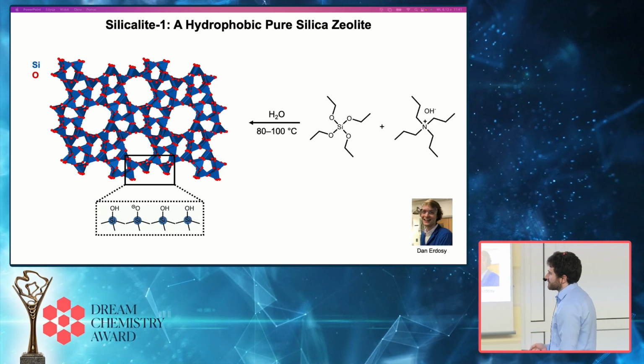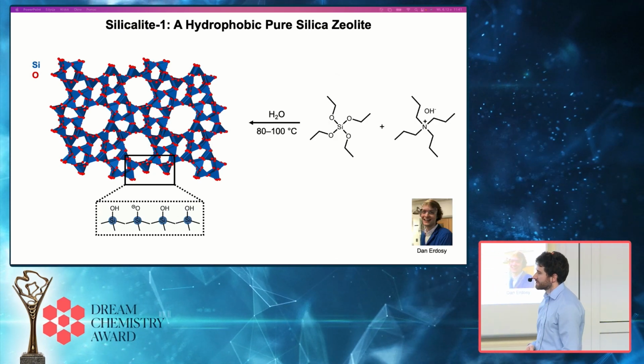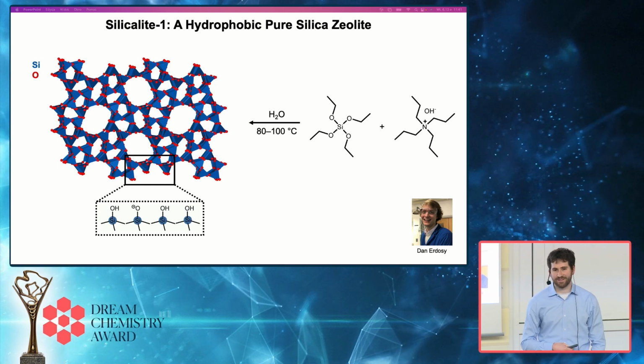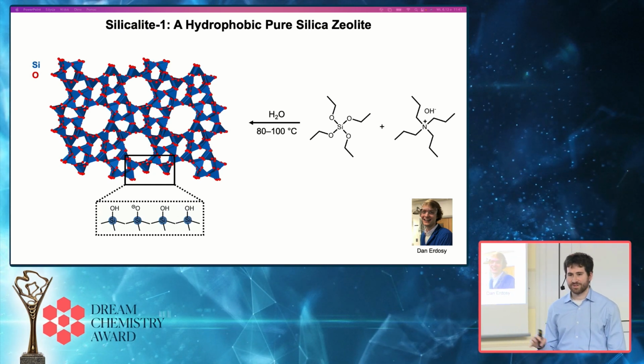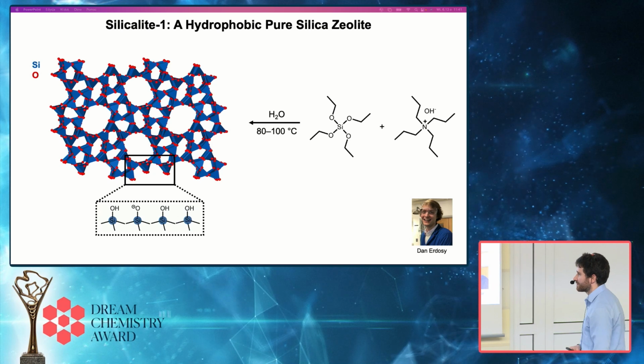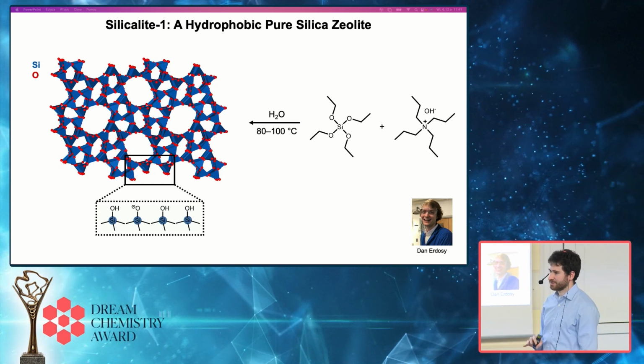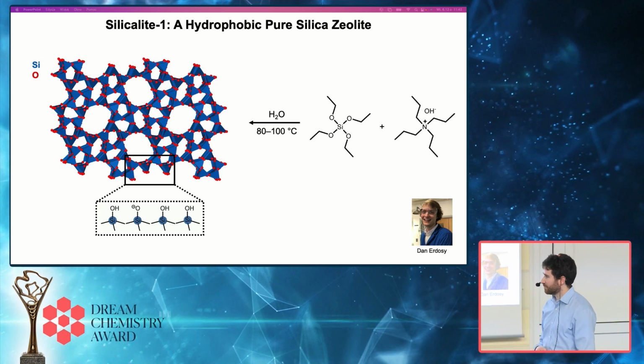And so a very talented graduate student in my group, Dan Erdosy, spent a lot of time optimizing the synthesis and activation of these pure silica zeolite nanoparticles so that we can make them with relatively uniform sizes and be able to actually disperse them in water.